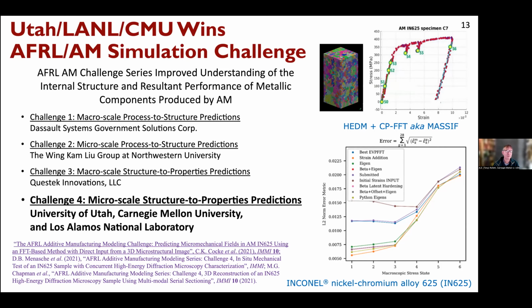But the Air Force Lab, AFRL, also put out a simulation challenge that was much more closely related to the kinds of techniques that I just briefly summarized. So what they did was to take a sample of printed Inconel, nickel alloy 625, measure about a cubic millimeter of it, publish the microstructure, publish the stress strain curve, tell us what the elastic properties would be, and then ask us to predict the state of elastic strain in 28 individual grains inside that measured volume that contains, let's say, 1,000 grains total. And this was challenge number 4 out of the 4 challenges that were offered.